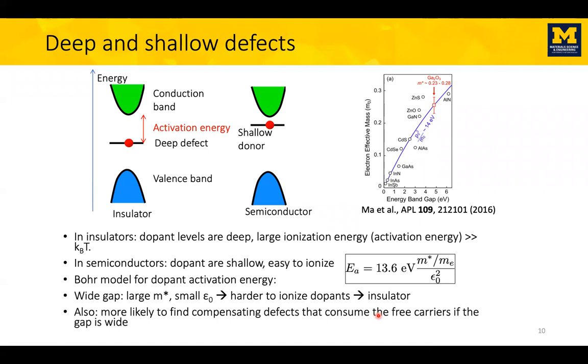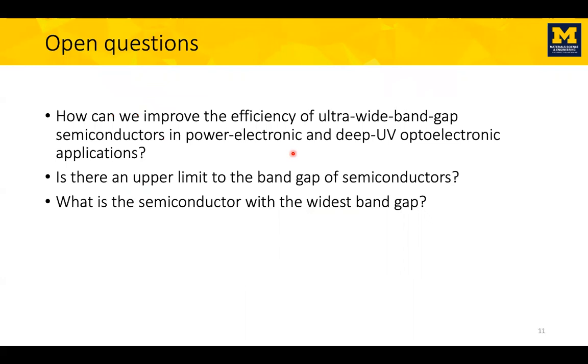But not only that, as the band gap becomes wider, you are more likely to form defect states in the middle of the gap and trap those carriers. For example, a defect that would have been in the band typically may appear in the middle of the gap, and the electron will go there and you would lose your electron. So it's a double challenge.